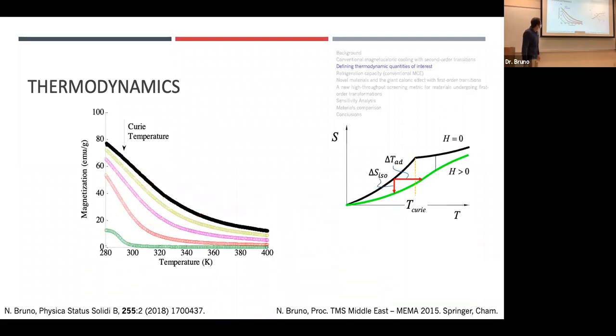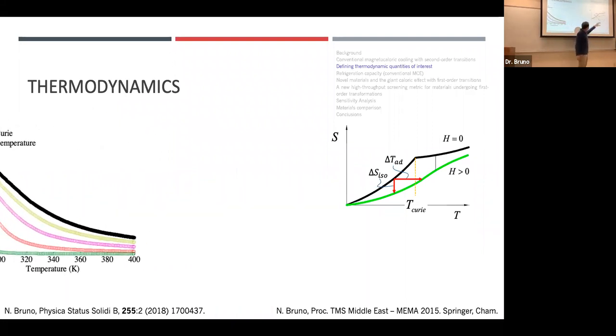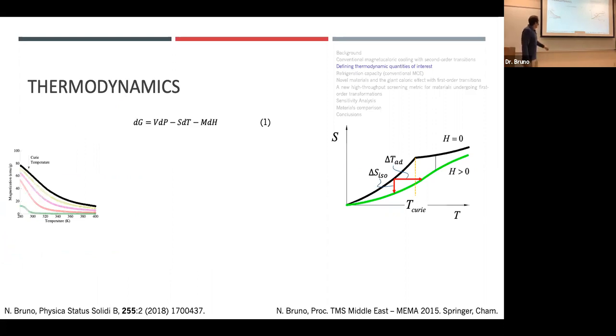So how do we use thermodynamics to quantify the magnetocaloric effect? That's the isothermal entropy change and adiabatic temperature change. Usually this is done with Gibbs free energy, which is derived from the internal energy of the system. We have to apply something called a Legendre transform to get into the Gibbs free energy. But we have dG, the change in Gibbs, equals volume times dP, which is d pressure, minus entropy times dT, minus magnetization times dH, d field. This is bulk magnetization. These are all volumetric properties.